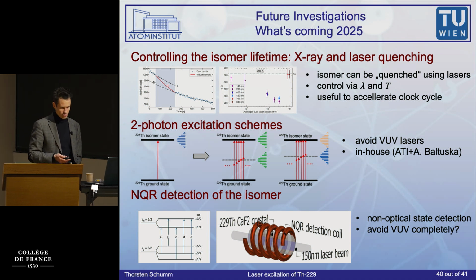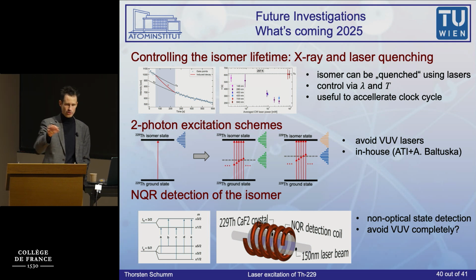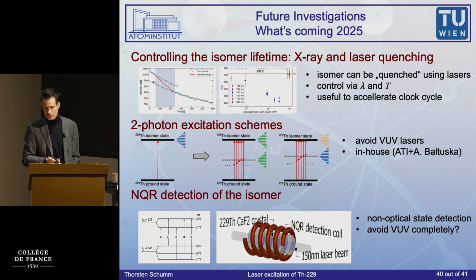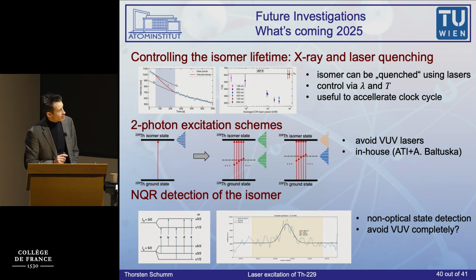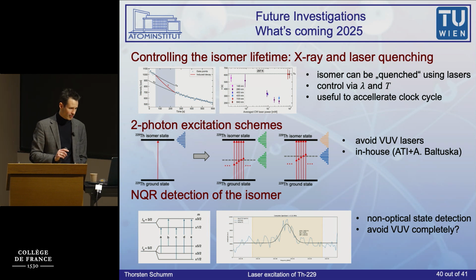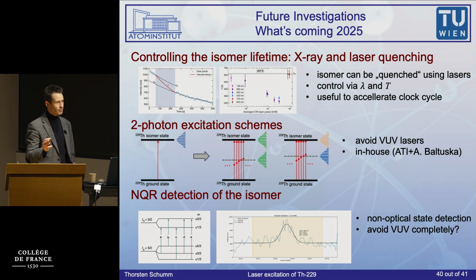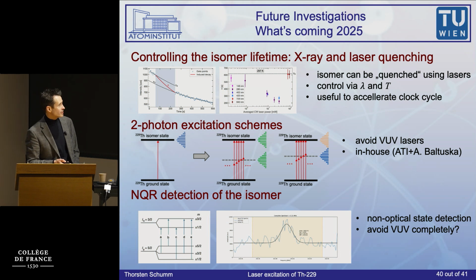It's called nuclear quadrupole resonance. You essentially apply a radio frequency and then you flip the spins and you hope to get a macroscopic magnetization that oscillates that you can read out in order to probe these levels here. And we started seeing a first signal on that. That's a non-optical experiment. That's really just a crystal in a coil in a cryostat.